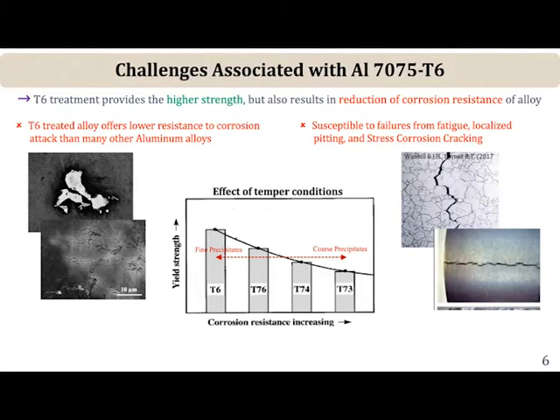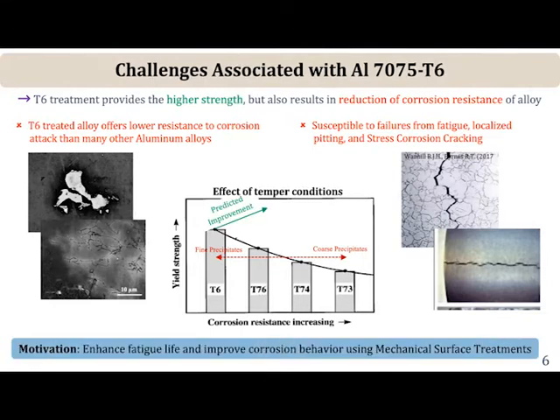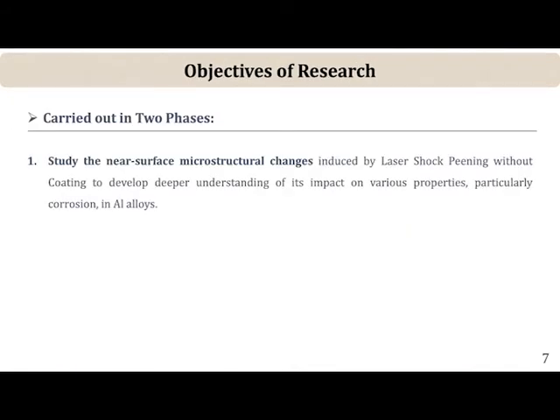So the question is, if I want to use the alloy in a high strength condition, then is there a way to simultaneously achieve protection against corrosion and stress corrosion cracking? And so the goal here really is to look at what impact mechanical surface treatments could have on improving the corrosion and stress corrosion cracking resistance of high strength aluminum alloys. So basically, Anurag did this in 2 stages.